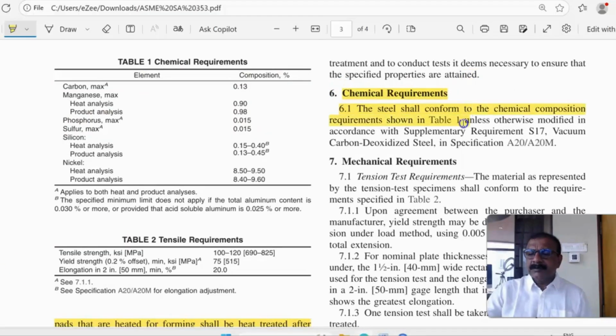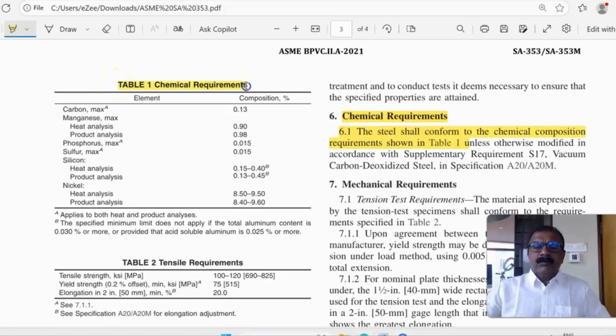Then chemical requirements as per table 1. This is table 1, chemical requirements. You can see carbon, phosphorus and sulfur. These values are applicable to both heat and product analysis. Whereas manganese, silicon and nickel have different requirements given here. You can see the nickel content is very high here. For heat analysis 8.5 to 9.5%, and product analysis 8.4 to 9.6%. Then for silicon there is a note B here that says the specified minimum limit of silicon does not apply if the total aluminum content is 0.030% or more, or provided that the acid soluble aluminum is 0.025% or more.